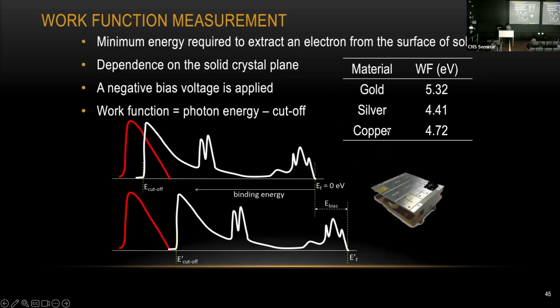And earlier we said we have a special stage called the biasing stage, and that can help you do some work function measurement. The cartoon shown right here simply illustrates how we do the work function measurement. For a work function measurement, we need to know what your Fermi level is and what your cutoff energy is. But when you do the normal XPS measurement, your high energy cutoff region is overshadowed by your spectrometer work function. So in order to see this edge here, we need to shift your entire spectrum. That's why we need to do some biasing.